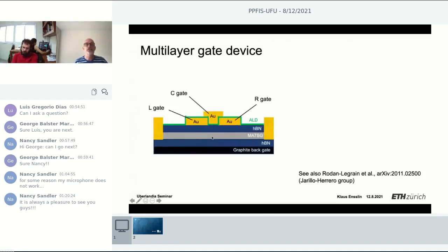three different regions here. We have a back gate that changes the entire density. Then we have these two outer gate electrodes left and right to tune there the electron density. And in the center, we have a gate where we can locally tune the density again. That is already interesting because you can make a superconductor with varying length. So this is the situation. We call this the density in the leads and the density in the junction. And this is an SEM of our sample.